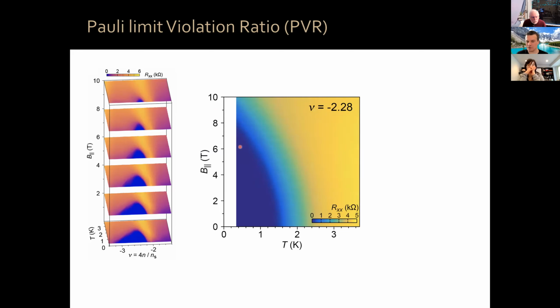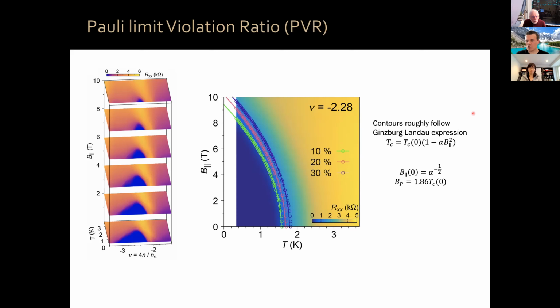This dark region is superconductivity. I can take any threshold that I want for superconductivity, 10% normal state resistance, 20%, 30%. It is the same if you take 50% or BKT temperature, okay? You can see that these regions evolve all parallel, okay? The contours follow this quadratic form, okay? So these are all parabolas, okay?